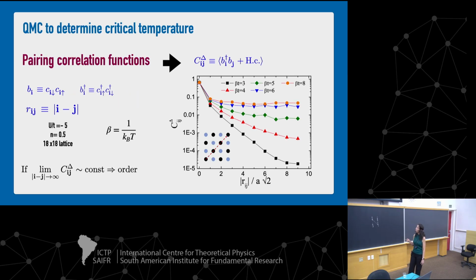And so what we wanted to do is use quantum Monte Carlo to find the critical temperature. Once again, we want to guide the experiments. If you don't know how cold you have to get to see these phases, how are you going to plan your experiments? And so we do this by calculating pairing correlations. So the pairing correlation is something like that. You destroy a pair at site I, and you create a pair at site J, and you see how this falls with the distance. And here, beta is the inverse temperature.